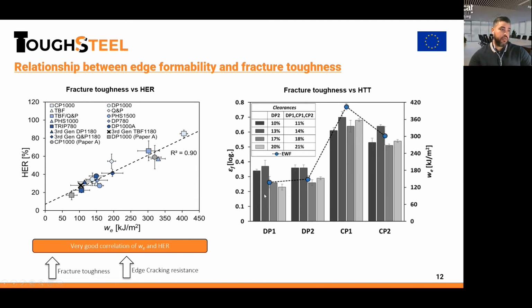That's the case for the hole expansion ratio, but with different experimental setups we have also observed similar trends. In this case, these are results from the hole tension test. Here, the bars represent values of fracture strains measured at the hole edge, so these are edge fracture strains. We can see a similar trend: the steels with lower fracture strains also show lower fracture toughness, as measured by the essential work of fracture, indicated by these blue points. On the other hand, materials with higher fracture toughness also show higher fracture strains. But it's also interesting to note that in steels with low fracture toughness, we can see a clear decrease of edge formability when increasing the cutting clearance, for example from 10 to 20, in this case of dual phase 1 and dual phase 2.